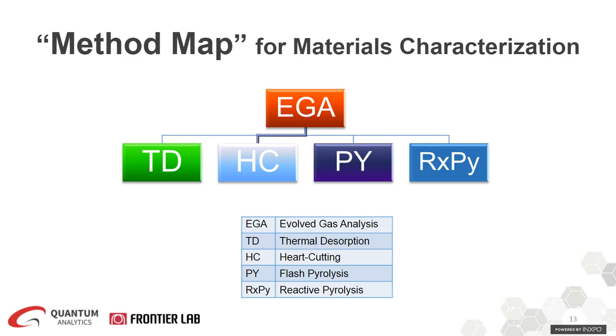So now that we mentioned you have multiple analyses using the multi-mode pyrolyzer, where would you start? So we developed a series of techniques as a method map to chemically characterize samples using this technique. So in this technique that is virtually applicable for any organic compound, from volatiles to high molecular weight polymers, the first step is to perform evolved gas analysis. Then EGA, evolved gas analysis, is used to determine the next step and guide you what to do next. For example, it will show if a thermal desorption step is needed or if a multiple heart cutting step is required. Also, EGA shows the optimal and proper temperature for flash pyrolysis to analyze the polymers, so you're not overheating or underheating your samples.